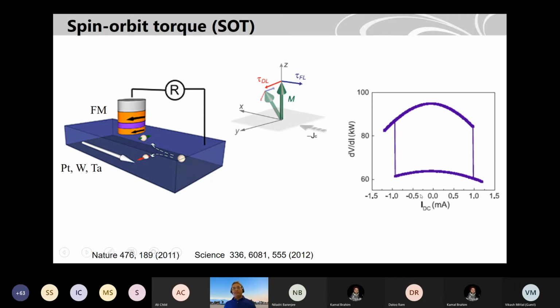And that's exactly what people have seen in this 2012 paper and 2011 paper here: when you apply a current in your metal, you see the change in the resistance of your device because you switch one of the magnets. And so this is called spin orbit torque. The spin orbit effect in this material and the spin polarization here exert a torque on your magnet, and this gives a switching. And this torque can be of different kinds. From different types of experiments, people can find out which torque is dominant in which material and which interface, because this is very sensitive to the interface here. There are torques like the damping-like torque and the field-like torque. The damping-like torque comes mostly from the spin orbit effects, and that is more useful for switching the magnet.